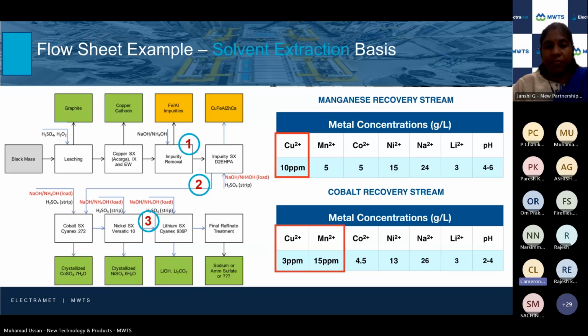And so here is a full flow sheet example, this is actually designed by Solvay using their solvent extraction process. You can see they do a bunch of different steps. Usually a solvent extraction to pull away the bulk of one metal, and then a polishing step. And then another solvent extraction to pull away the bulk of the metal, and then a polishing step. And so what we're seeing here is, even through their impurity removal process, there's still too high levels of copper and manganese in these different product streams. So from the very beginning, copper is a big problem.